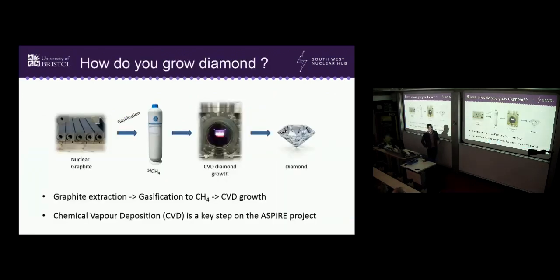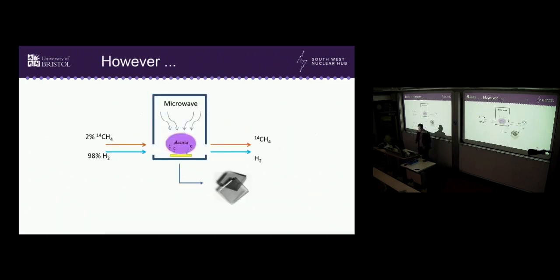So with this process, we process our graphite, we create essentially an isotopically labeled carbon-14, we grow the diamond, and then we would finish off the diamond device by putting on the metal layers on the outside, which is a technology we've already mastered, and we use that for the diamond detector. So a number of different steps, but one of the key steps is chemical vapor deposition, because this is a well-established process, and De Beers use it all the time. But this is the first time in history where actually people have wanted to grow isotopic diamond. It's the first ones ever, in fact.